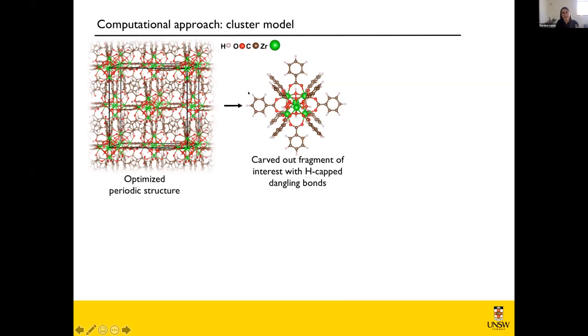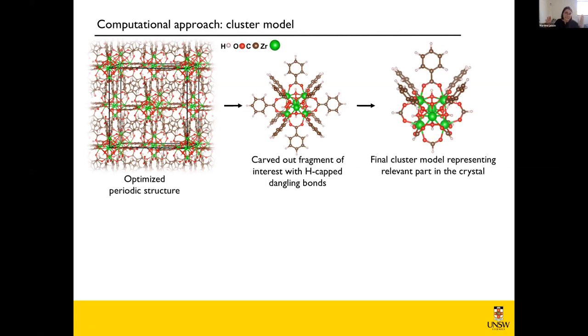So we cut it out, and you can see here that the BDC linkers have lost their carboxylic groups, but that means that I would have had a dangling bond, and so I just saturate this dangling bond with hydrogen atoms. And then we go and reduce further the size of the cluster to really just have what we need, which is just these two zirconium atoms that can be exposed upon removing the linker and can then interact with arsenic or other species around in the environment.